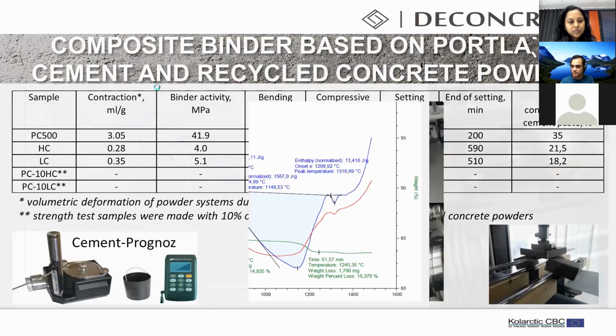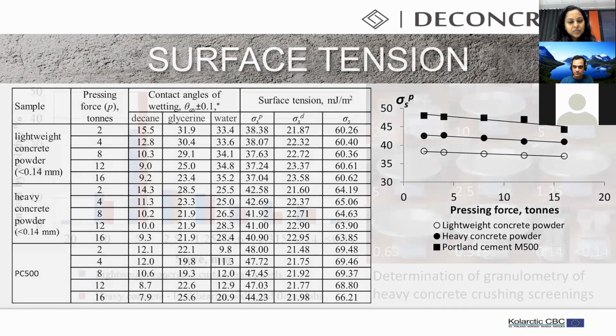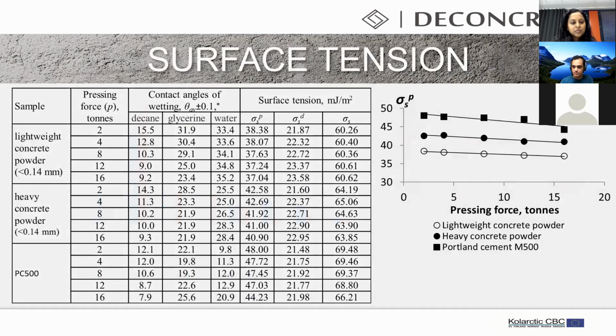Which test method was used for testing surface tension for fine recycled concrete? So we used the OWRK methods, Owens, Wendt, Rabel, and Kaelble method, which can be used to obtain two values of surface tension. I need to show it in the slide. Yes. Slide: polar and dispersive components of the surface tension. So, for example, last row surface tension, first column is polar component, second dispersive component, and the last one is the sum of the previous two.